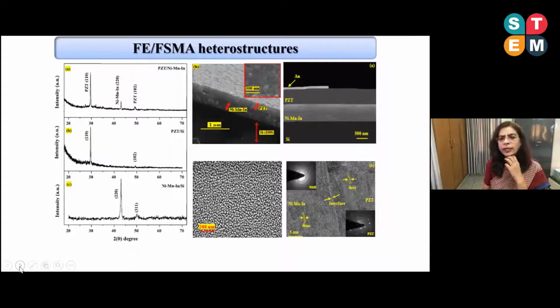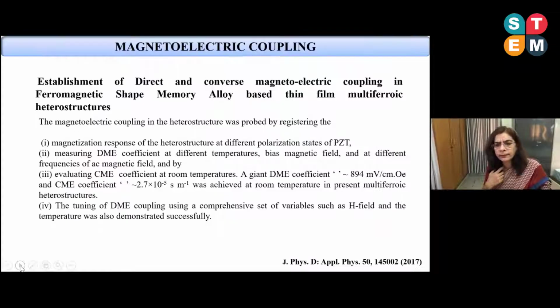This is a TEM picture of this heterostructure. We have been able to even see the planes with this FSMA PZT heterostructure. The value of the interplanar distance matches perfectly well with the theoretically calculated values.